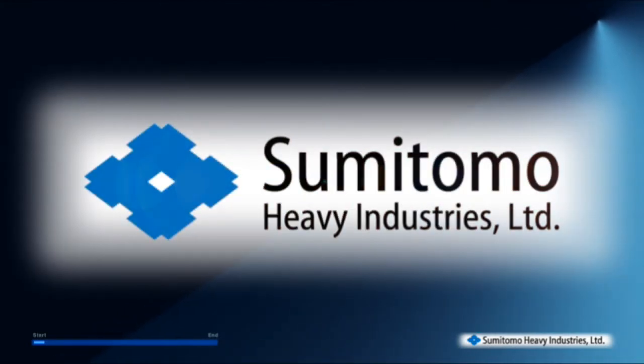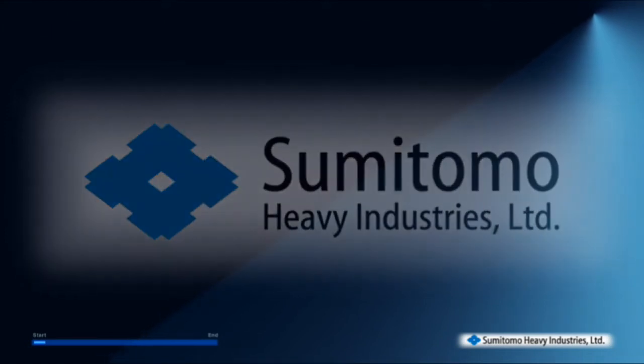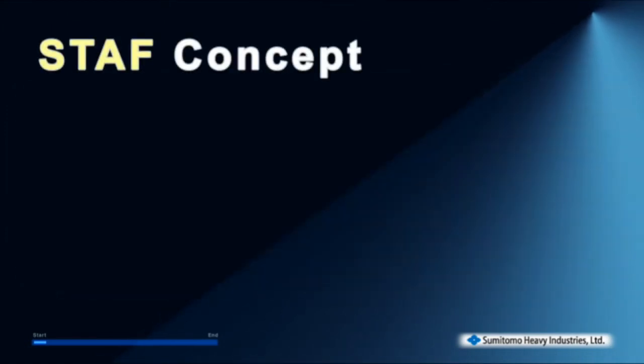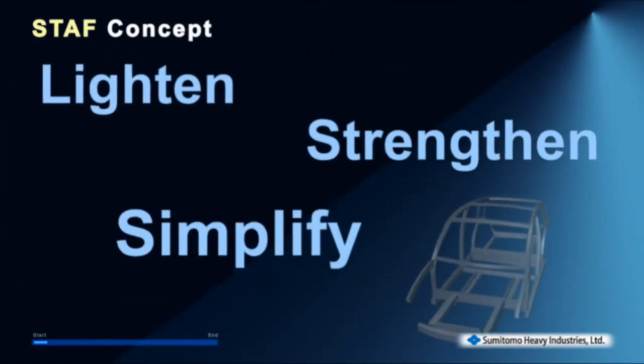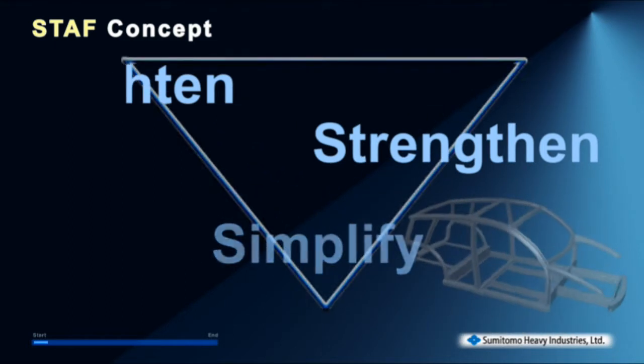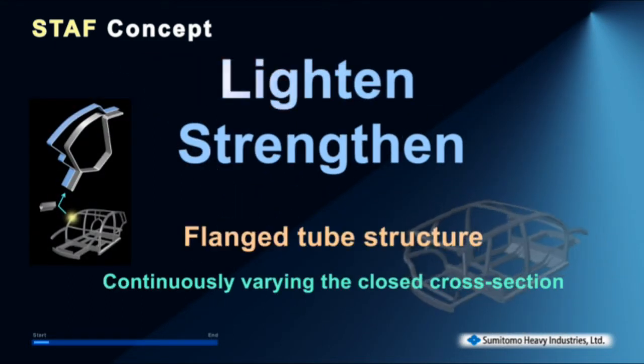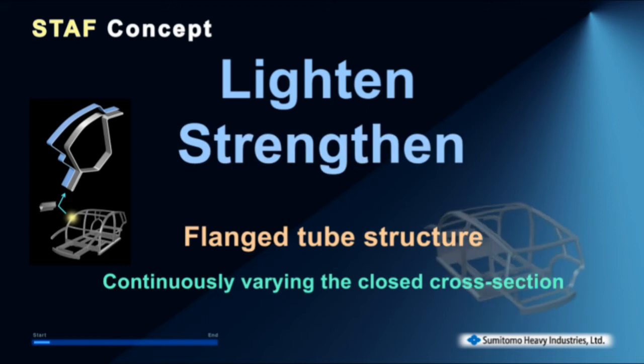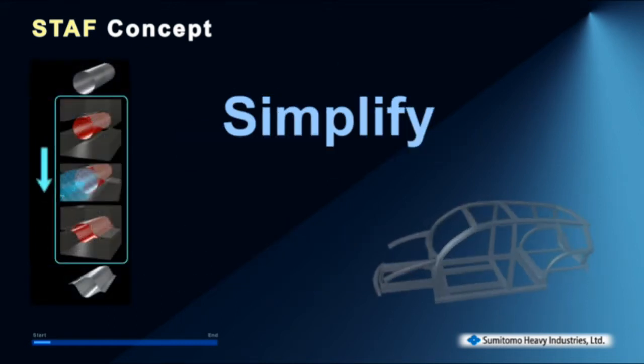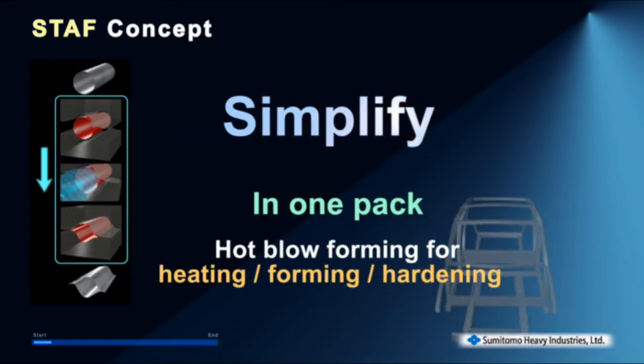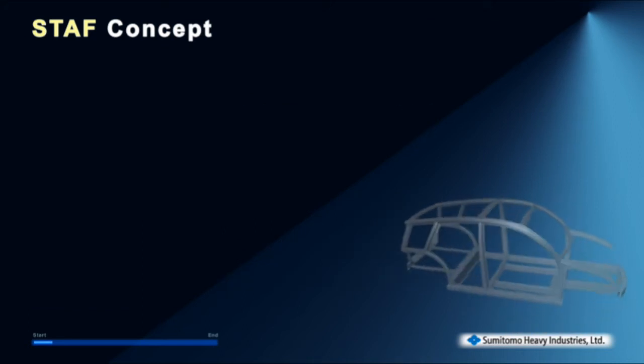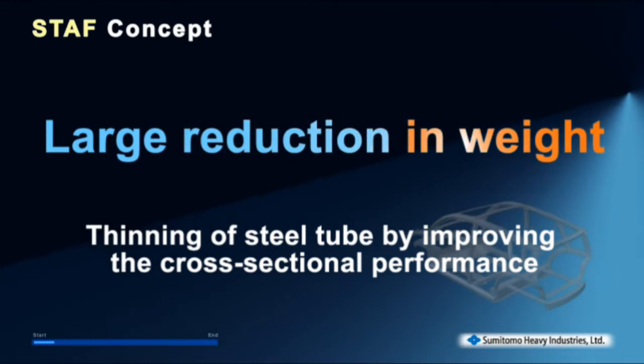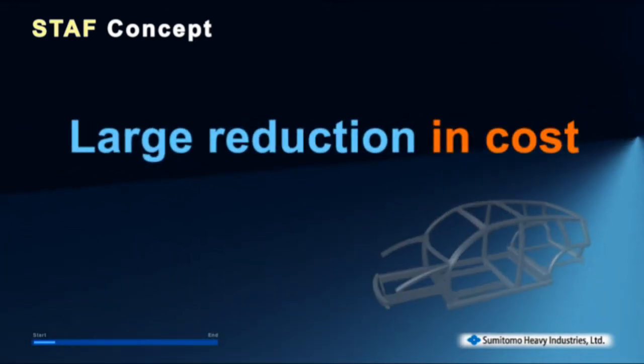The STAF system is a technique that applies heat to pipes and uses high-pressure air to simultaneously blow, mold, and quench. The concept is light, strong, simple. We can make a 1,500 megapascal class closed cross-section with a flanged continuous irregular shape, all molded in one process. We expect this breakthrough to reduce weight by around 30%.